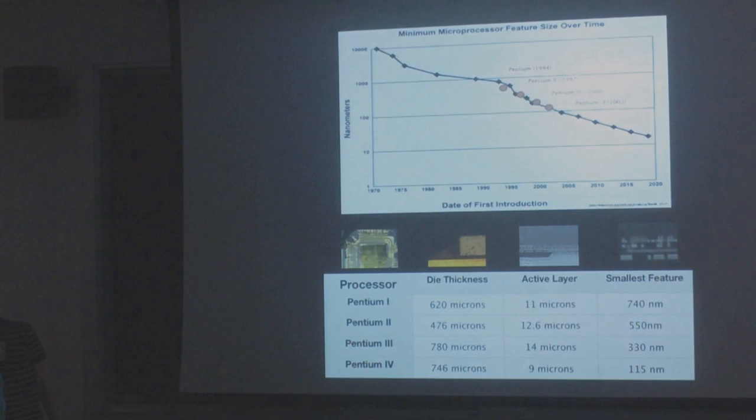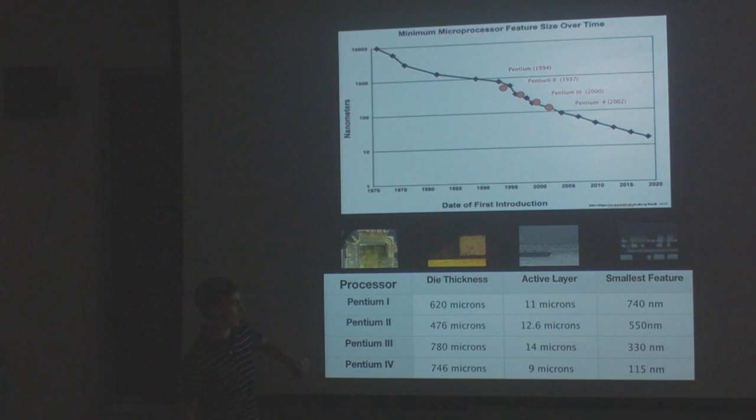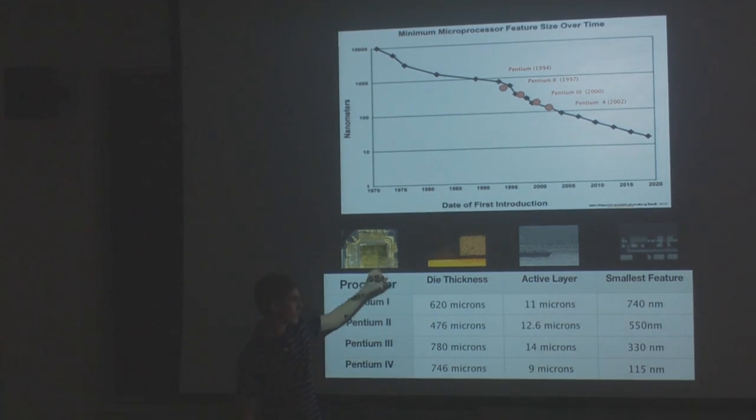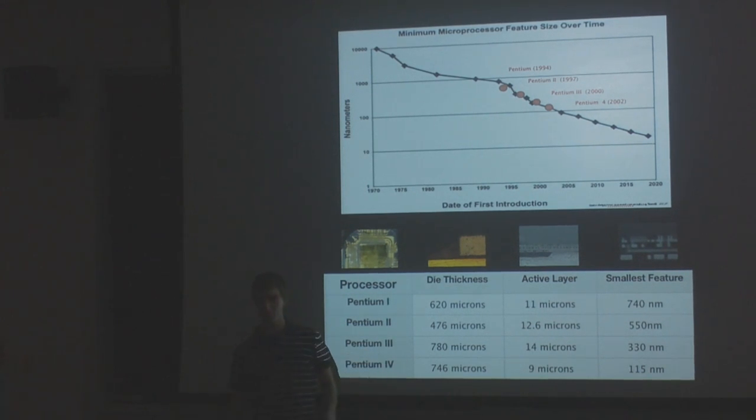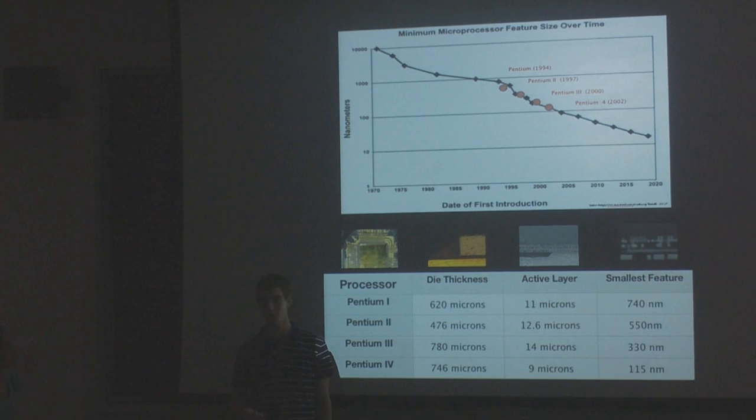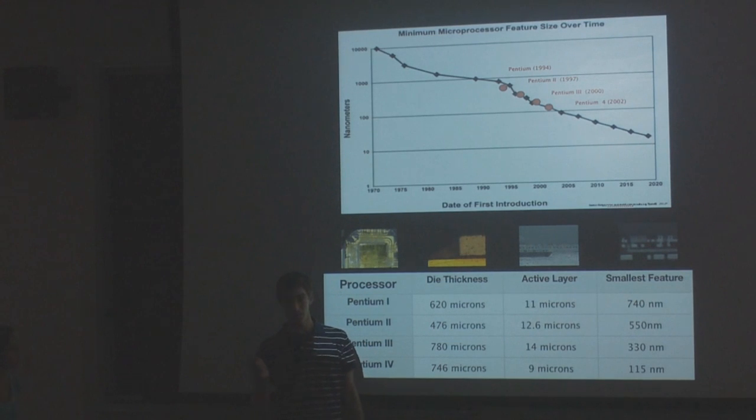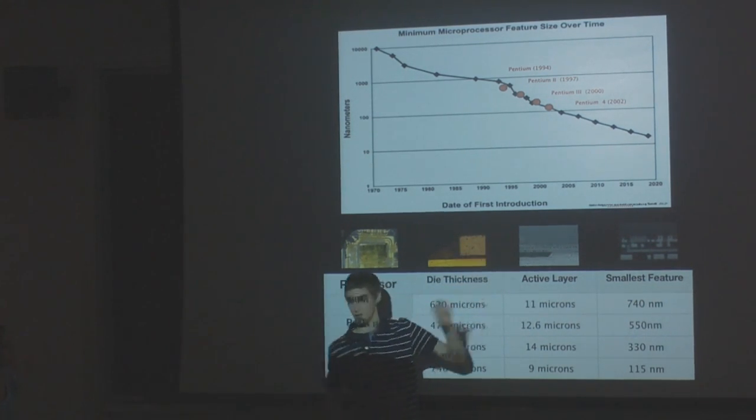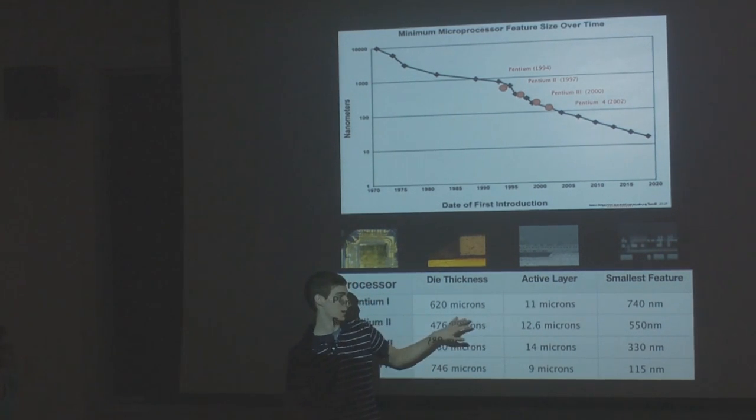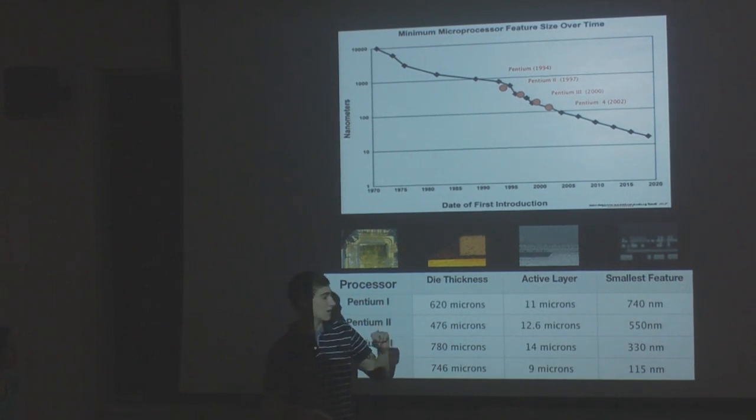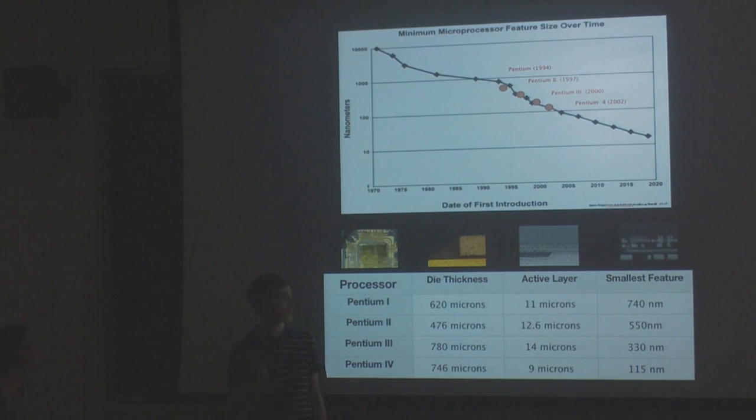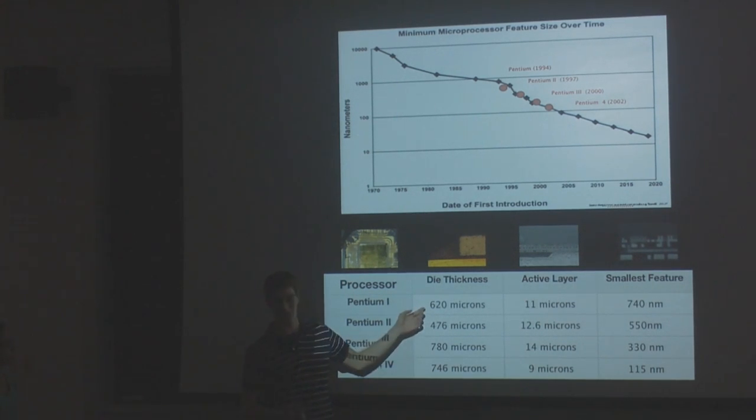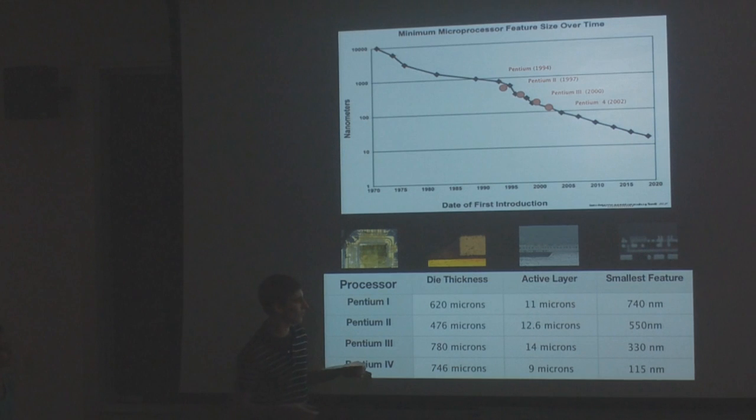Now let's actually look at what this looks like in Moore's Law. These are the different processors, and the die thickness, which is this area—the thickness of the silicon—you can see in the different Pentium processors stayed pretty much the same. They got pretty thin in Pentium 2, but then they decided that that was too thin for processing reasons. Again, we had trouble imaging the Pentium 2 because it cracked so easily. The active layer, this was impressive. The active layer, which is just this area where all of the transistors and metal interconnects are, is extremely thin compared to the actual body of silicon. And we knew that, but it was just interesting to get a sense of scale for how thin that layer really is. It's very, very tiny. But again, the reason that the entire die has to be so thick is because otherwise it would just break and you couldn't get a full wafer.